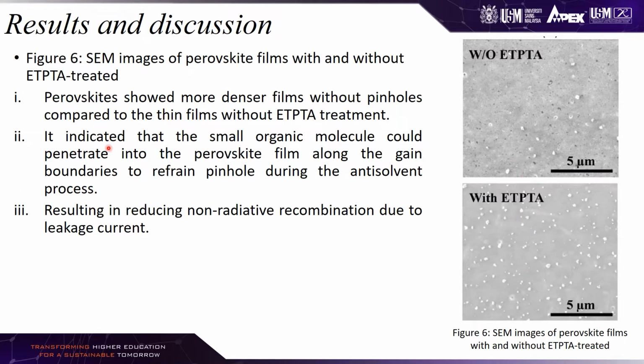It indicates that the small organic molecule could penetrate into the perovskite film along the grain boundary to remove pinholes during the anti-solvent process, resulting in reduced non-radiative recombination due to leakage current.